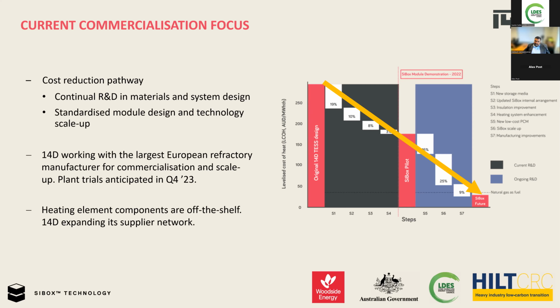Over the last year, we've also been working with one of the largest European refractory manufacturers for scaling up our technology. So initially, our products were using a casting method, which was a lot more manual intensive, labor intensive. And over the last 12 months, we've changed that recipe and made it compatible with a press product, which, I mean, about 1 trillion or so bricks are made every year, and these are refractory bricks. And the technology to make these bricks has existed for over 100 years, a lot more than that, in fact. So the pathway for scale up for us, because of this, becomes much easier compared to a lot of the other proprietary manufacturing methods. And we're anticipating plant trials with these new recipes in the near future.